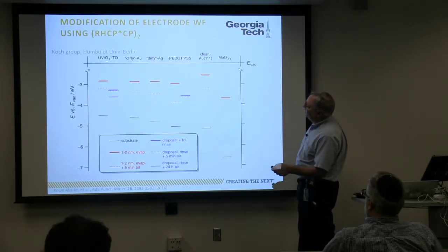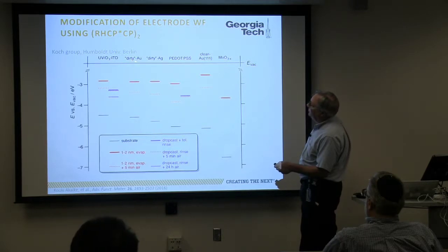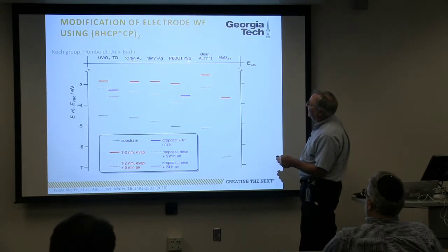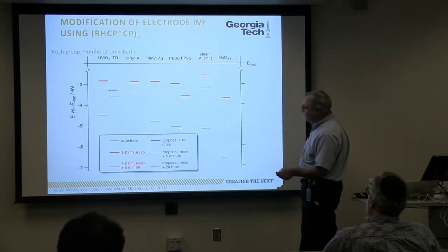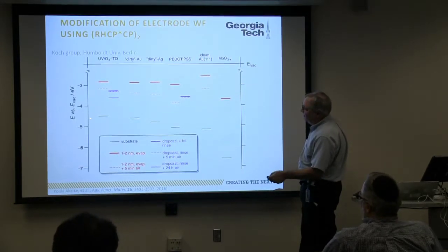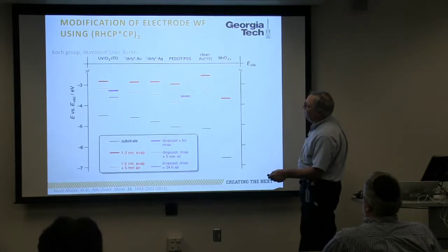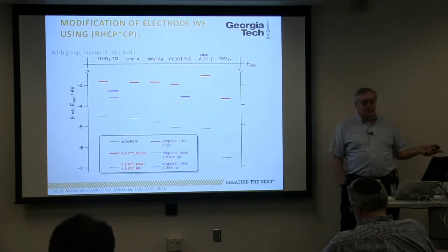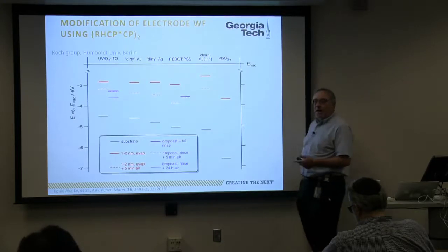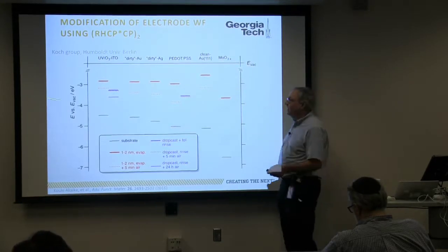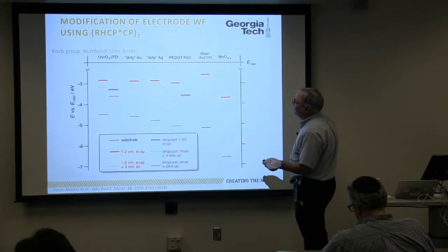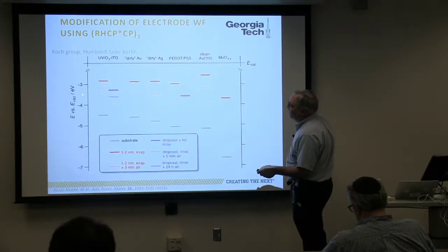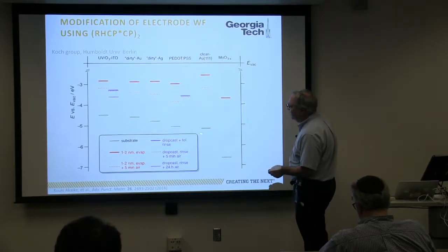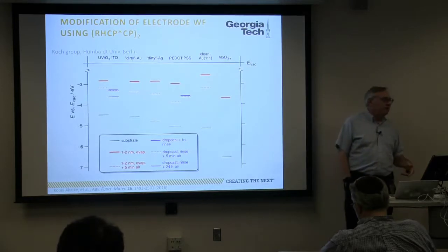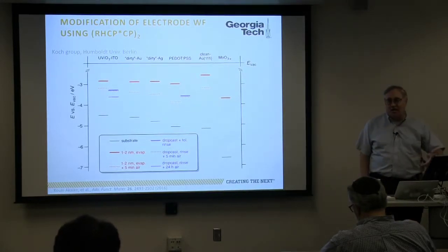And we'll show a few examples. So here are a bunch of different materials: ITO, dirty gold, dirty silver, PEDOT:PSS, which is an organic material, clean gold, moly oxide. And here are all their work functions in the absence of doping. And then we put down literally a nanometer or so of dopant on top. By and large, a monolayer. And now what you can see is that all these work functions get below 3. So we've taken materials that would normally be good anodes and we've turned them into cathodic materials.